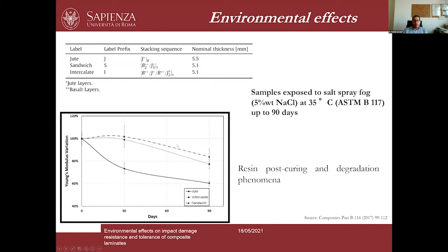So in this case, here you can see the effect of this aging on, for example, the Young's modulus. We can see a significant decrease for jute-based composite. This decrease was somewhat reduced by the presence of mineral fibers, such as basalt fibers.